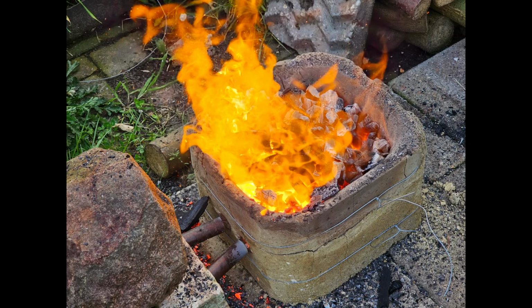To summarize on the hearth refinement technique, all the mythological qualities that have been attributed to Ulfbert swords can be explained by the hearth refinement technique. First of all, it is quite easy to create hypereutectoid steel via the hearth refinement technique, in particular suitable for rattlestone bloomery iron. Next, slag will be expelled out of the bloomery iron because the metal is made almost liquid, and the calcium-rich hardwood ash slag bath will absorb some of the phosphorus out of the steel matrix into the slag. But also manganese will be or can be reduced out of the slag into a metal alloy proper, vastly improving the characteristics of the steel altogether.